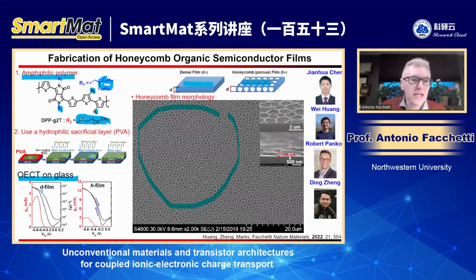And you see here that when we compare the OECT performance for the dense and the honeycomb film, the porous film, the hysteresis is reduced and the current is higher. Here you have 12, you have 8. So also for this polymer, porosity works better in terms of charge transport. But the key question is about mechanical properties. So the question is, are the porous films more elastic compared to the dense film?